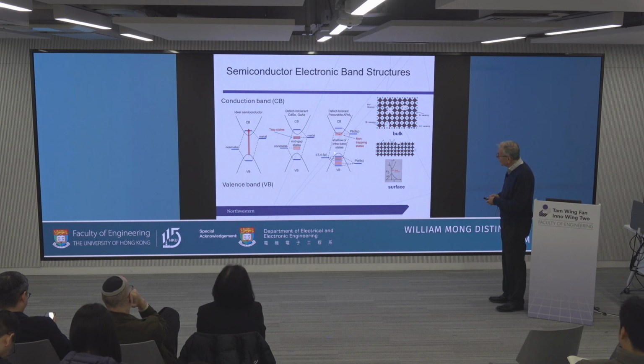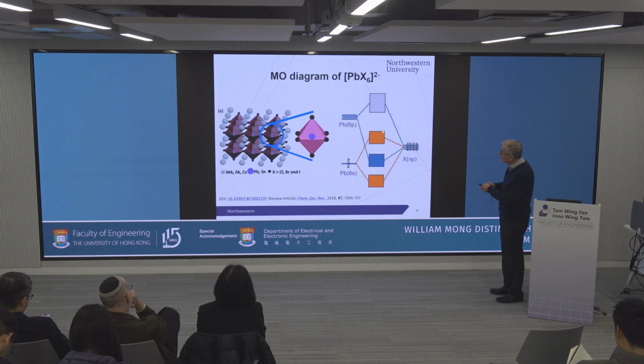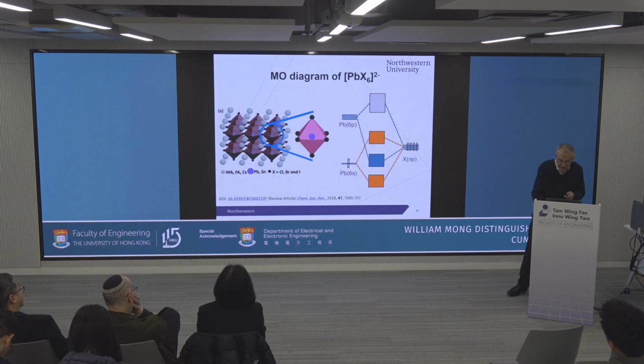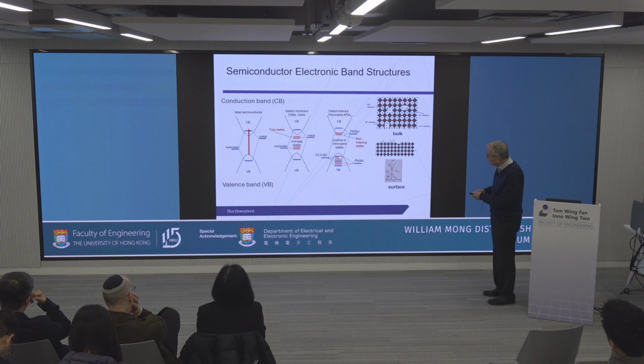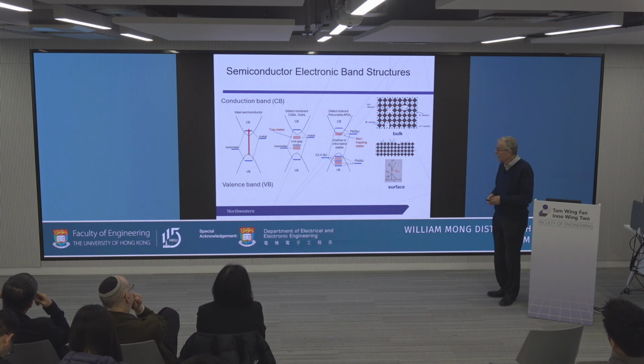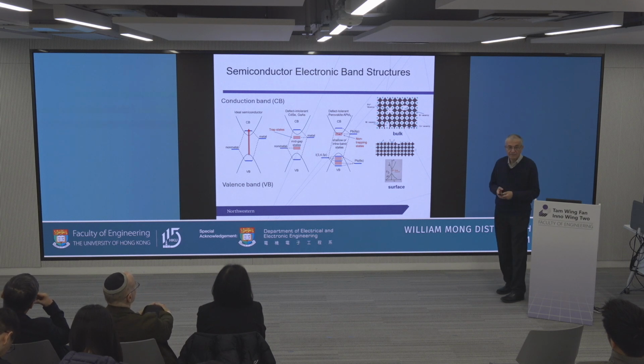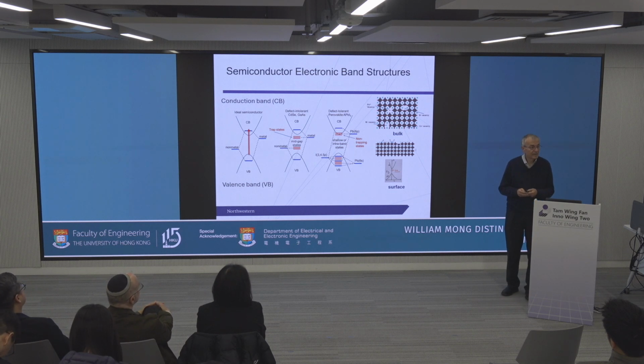The perovskite, when you have similar defects, these states don't go into the band gap. They go inside the band. Why? Because given that this is antibonding, anything away from that will make it bonding. If it's bonding, it will come down. So the defect removes antibonding states, and therefore the state goes inside this band. If it's inside the band, it's not a trap. So this is defect tolerant, and this is defect intolerant. Now, that means you can have this lousy lattice, and you can still get it to work because of this defect tolerance.